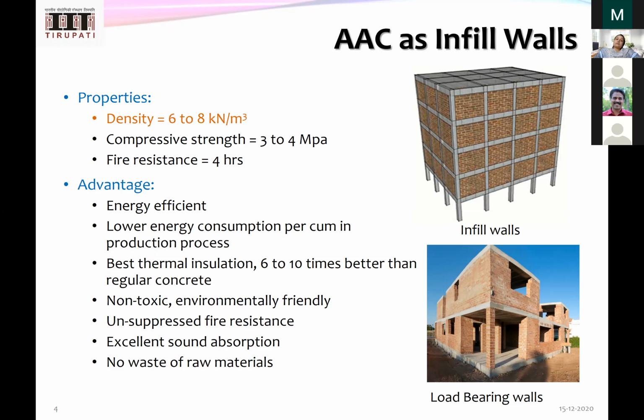So because of all these advantages, if you look into AAC block as a building material, mostly it is used as infill walls. Of course, in some cases people recommend using it for load bearing walls. But we found that as load bearing walls, from a long term point of view, especially long term effects like creep and shrinkage, which are very significant in these bricks, normally create failure in the system. So it is better to avoid this brick for load bearing walls, but it is a very suitable brick material for an infill wall concept. There you can use this particular brick as an infill wall.